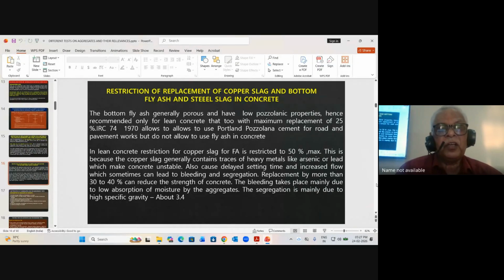When we come to fly ash, bottom fly ash is generally porous and has low pozzolanic properties, and is recommended only for lean concrete, with a maximum percentage of 25%. In fact, if you go to IRC 74:1970, it allows only Portland cement for road and pavement, and does not allow the use of fly ash in concrete.